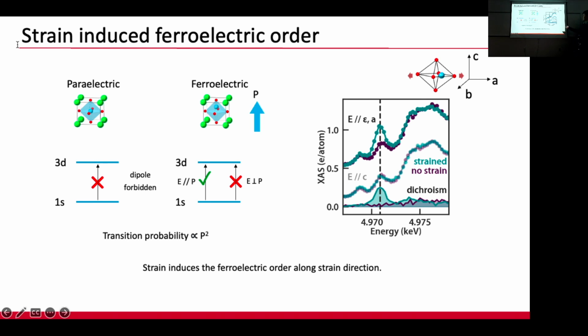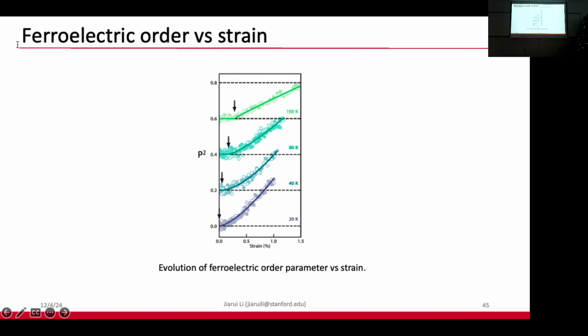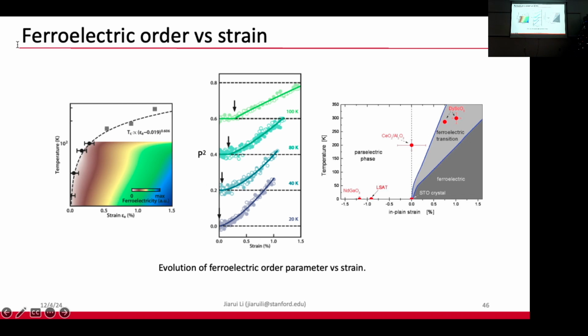We can track this signal as a function of strain at different temperatures, and we see a very highly temperature dependent evolution of this strain and ferroelectric order parameter. So we can reconstruct a phase diagram. First, we can identify a phase boundary between the paraelectric phase and the ferroelectric phase, and this is the phase boundary, which is very similar to what people already know in the literature.